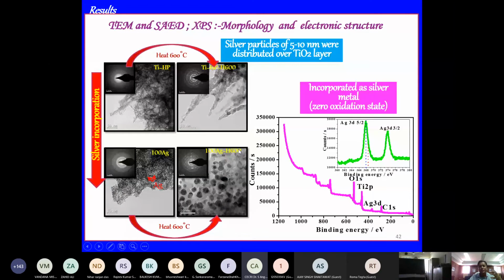Here you can see the transmission electron microscope image, where you can see how silver nanoparticles of 5 to 10 nanometers are decorated over this surface modified titanium metal. We have also confirmed that the silver is in the zero oxidation state. A lot of fundamental aspects we also study during the course of our research.